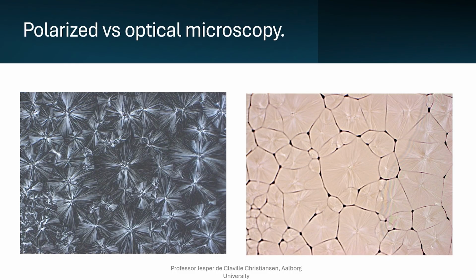Furthermore, what we observe when we recycle the polypropylene, if you look at the left-hand side, you can see that the crystallites are not even in size. We start to get variations in size, but also on the right-hand side, in non-polarized optical microscopy, you can see that there are also interfaces between crystallites.